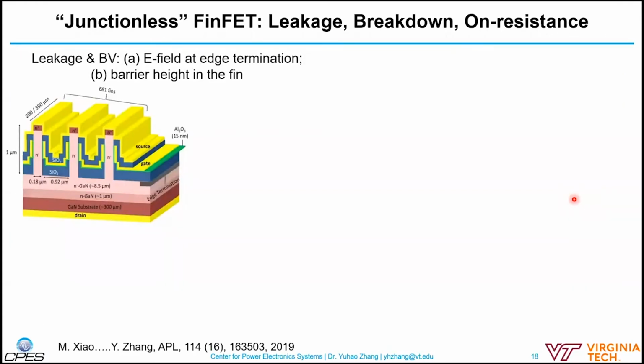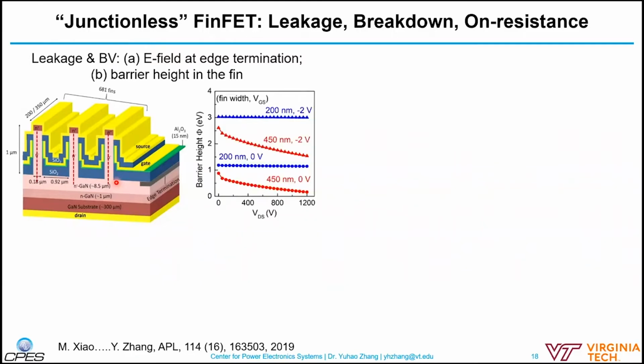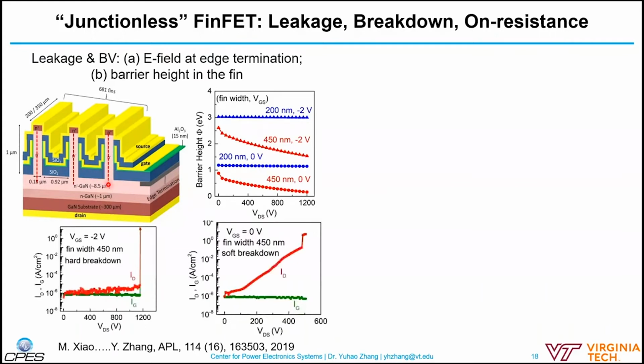And this device is also very interesting because it doesn't have a p-n junction, so it's very different from many conventional power transistors. So we call it a junctionless transistor. For example, if we look at the leakage current, the breakdown voltage is no longer dominated by the p-n junction. From our study, we show these are short channel devices with a dipole effect, and the breakdown voltage is many times controlled by the potential barrier in the fins. So essentially, in relatively wider fin devices and at different gate bias, we can observe two very different breakdown mechanisms in a single device.